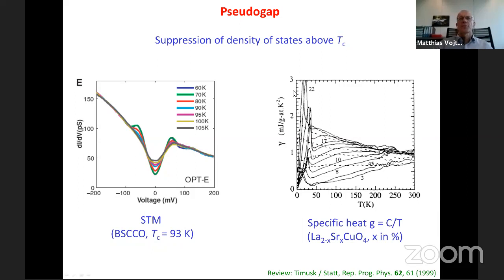This plot here shows the specific heat coefficient. So this should be gamma, I'm sorry, which is C over T as a function of temperature. The superconducting TC in these materials is somewhere down here. It's below 50 Kelvin. But what you see is that this quantity, which in a metal should be constant, starts to go down at temperatures far above TC, already around 200 Kelvin. So there are signatures of a gap, or actually a partial gap.